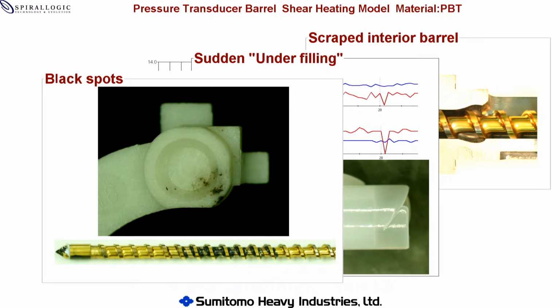We examined several production screws after extended production. You can see the carbonization occurs only in the compression zone of the screw. Thus, the cause of the black spot is also coming from the screw design. Material carbonization and black spots are unavoidable using screw designs with the compression zone, even with the surface-coated or chrome-plated screws.